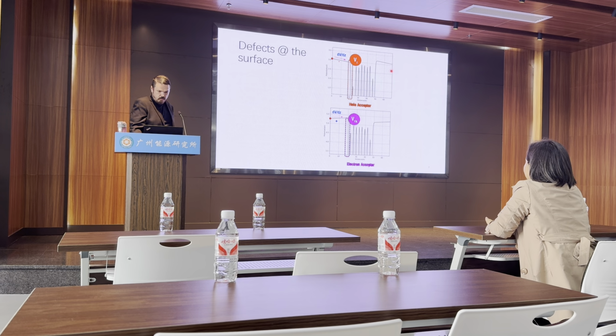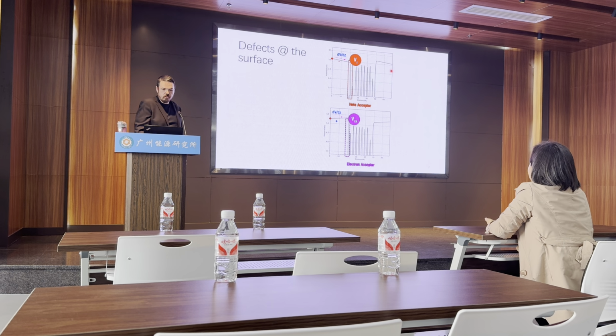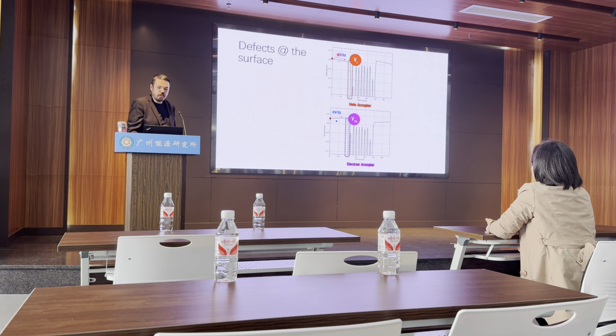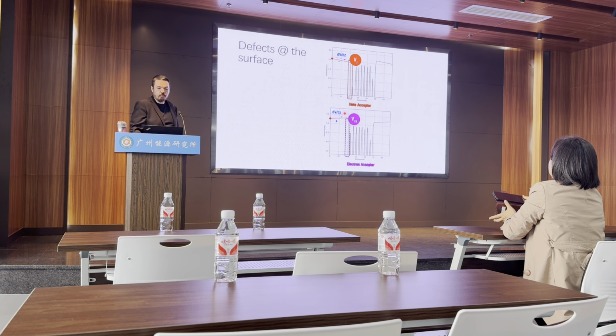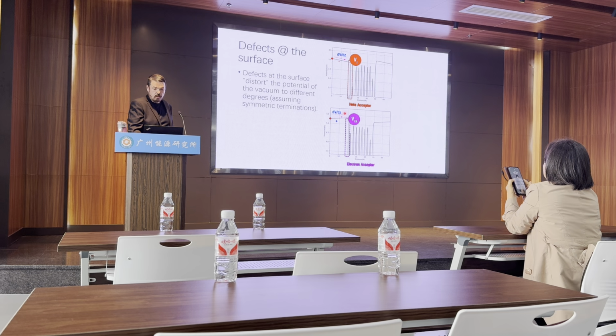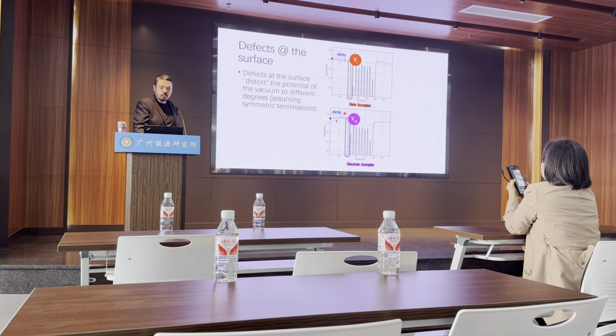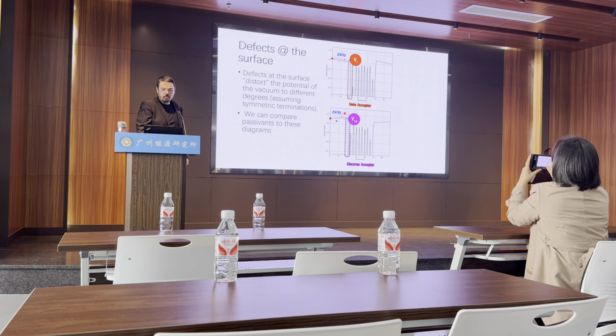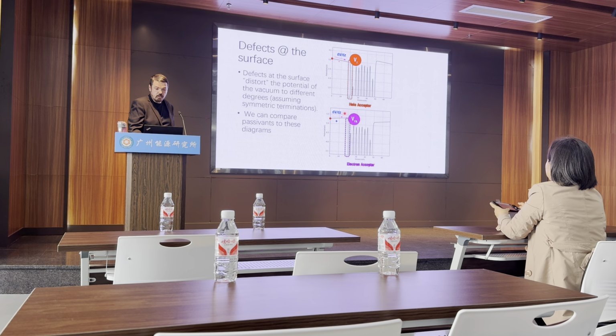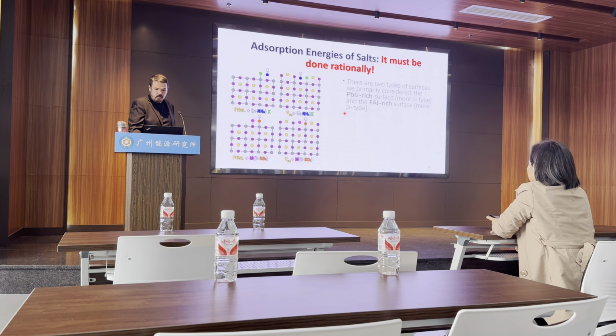Point 1, right? So when we talk about work function change, see, when we introduce an iodine vacancy, the work function shifts. So the potential in the vacuum space shifts downwards. And when we see this, we know it's a hole acceptor. When it's sloped upwards, it's an electron acceptor. So actually very convenient. So at a glance, we know a lot already about any kind of passivation we do. So we can compare basically any passivant to any other passivant just at a glance. And that's cool.